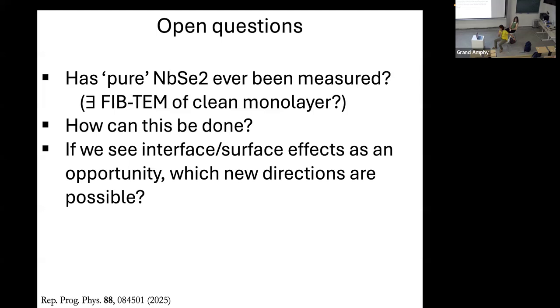And then the second thing I was going to say is the CDW. I don't know how this merges with what you know, but I saw a paper very recently that did the Mo substitution into Nb, and basically at a very small substitution fraction, they killed the CDW. So it seems very sensitive. Did it affect the superconductivity? What was interesting is that you put Mo in, a very small fraction of Mo, and the superconductivity actually gets better. So the TC goes up, and they claim that this is because they killed the CDW. I can accept this. And then after that the Mo basically kills superconductivity because you're going to MoSe2, which is a semiconductor.